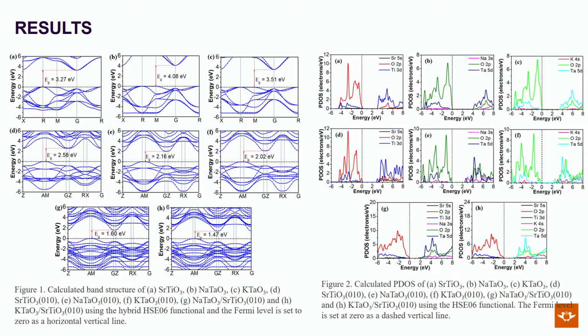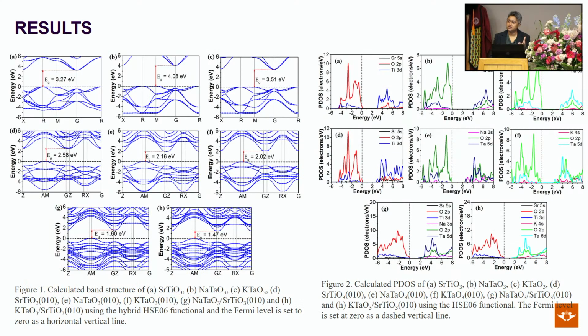So some of the results that we looked at showed us that our coupled material actually followed a type 2 band alignment. The first thing that we looked at was band structure. This is important because you want to compare your pristine materials with the new materials that you have made. You want to see that the band gap has actually decreased so that your material can absorb in the visible region. If you look at these diagrams, you can see we moved from high band gaps such as 3.4, 3.5 to 1.6 and 1.7. So it has reduced significantly after the electronic coupling.